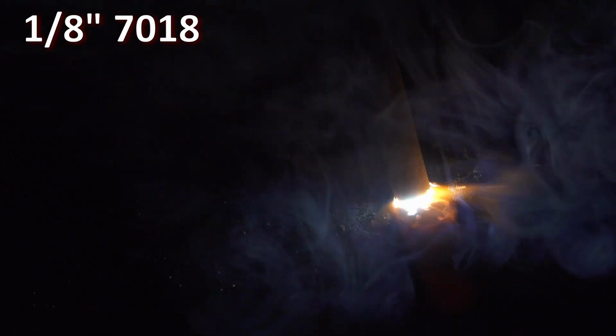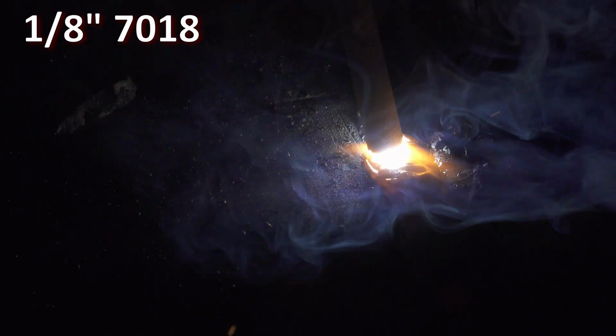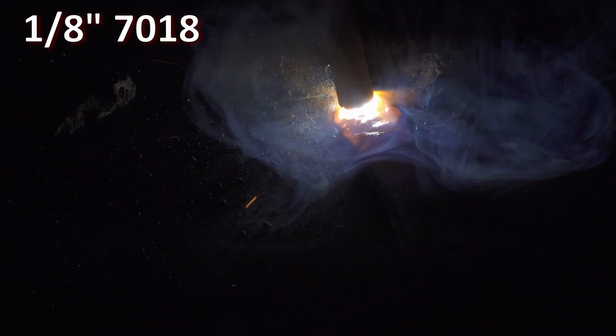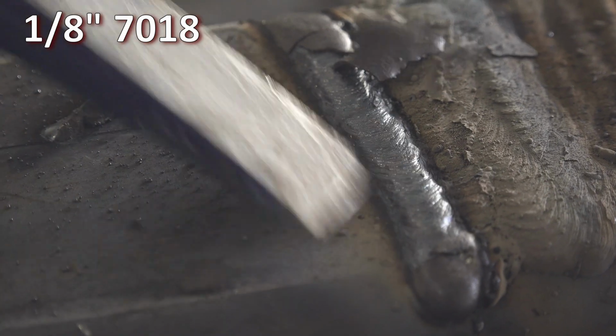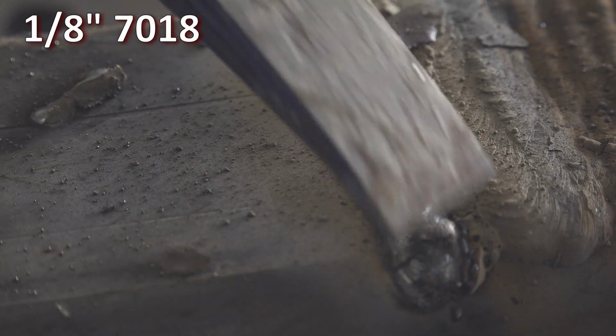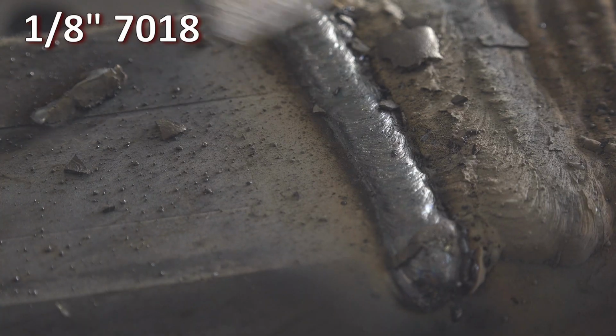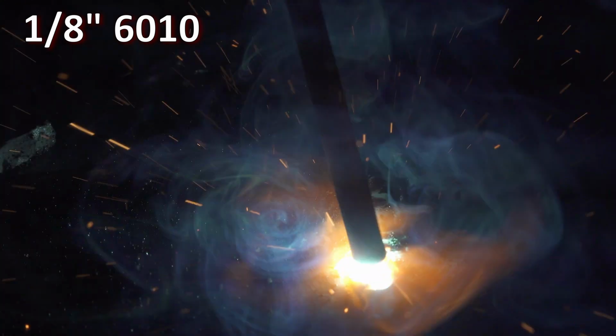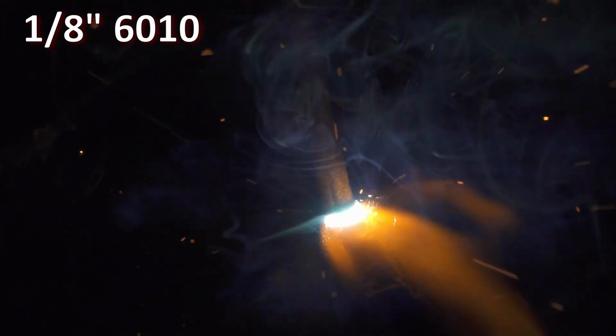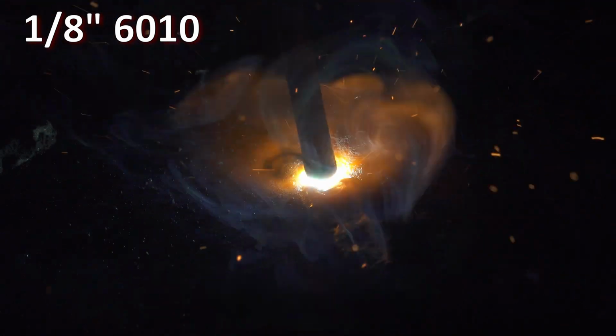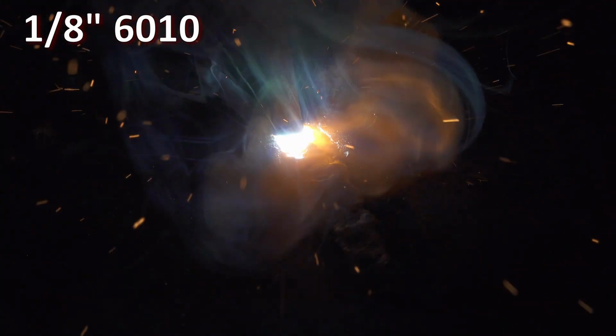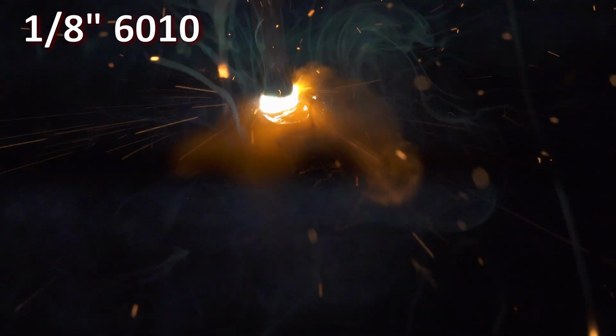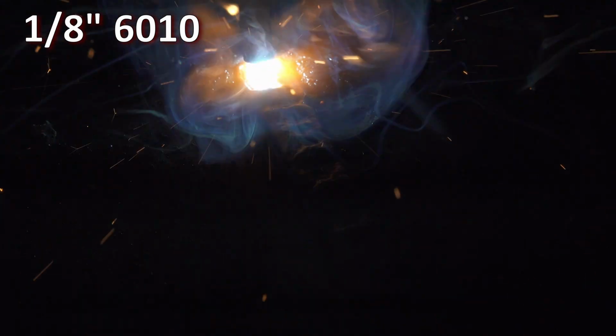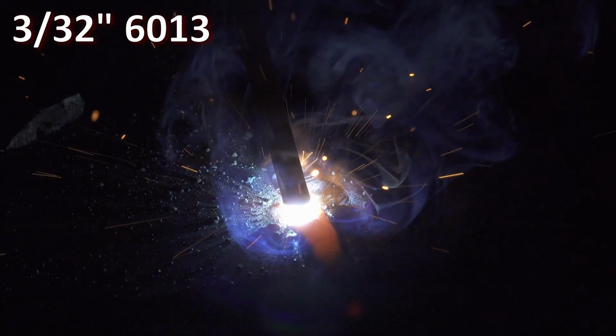The stick welding arc is very smooth and quiet. Hot start works and gets pretty aggressive when turned up. The arc force makes a less dramatic difference, but it did seem to be working. Maybe I'll do some testing to try to quantify the output changes it makes at some point. I also tested this machine with 6010, and it ran 3/32 and 1/8 inch 6010 just fine. There isn't even a separate mode for 6010, it just works. And it tolerated being set on the cold side and even kept going through a bit of long arcing, though if I got too wild, the arc would go out. Still, overall, I thought the stick mode was pretty good.